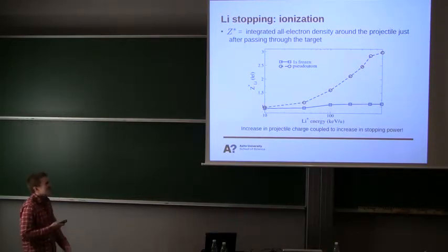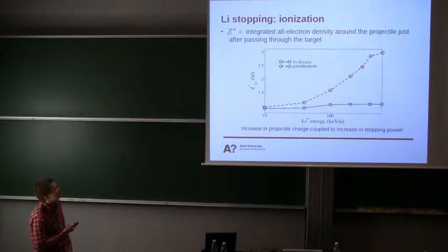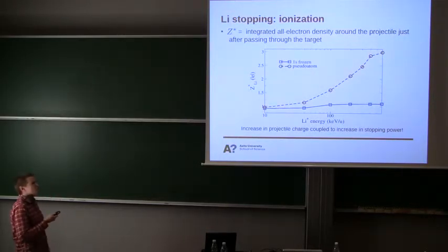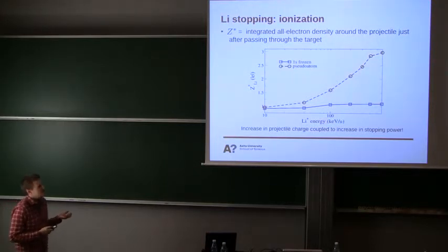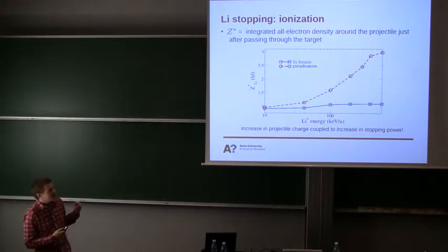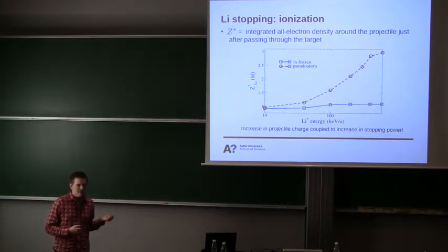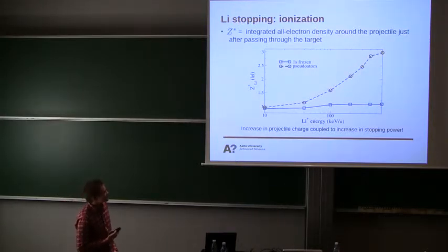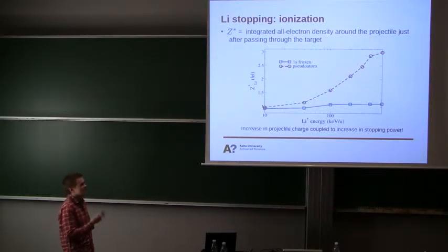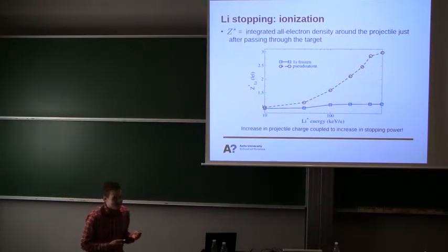Okay, I'm getting close. While we include 1s states, we see that the ionization of the projectile increases towards higher energies. From the previous slide, you remember that this increased ionization is connected to increasing deposited energy, or stopping power. So from this point of view it's also important to include the 1s state explicitly.